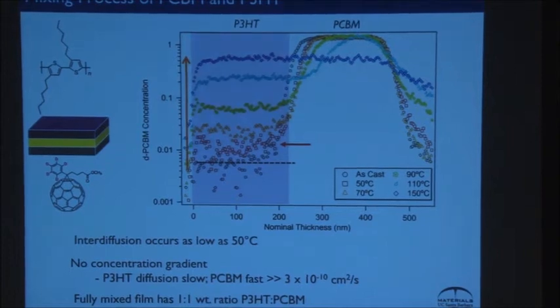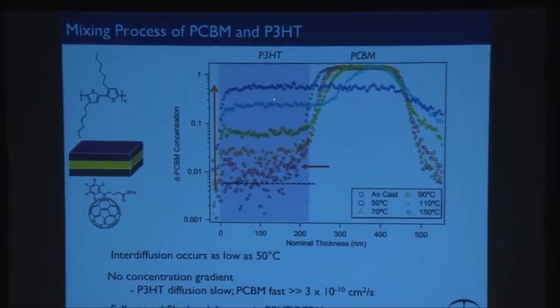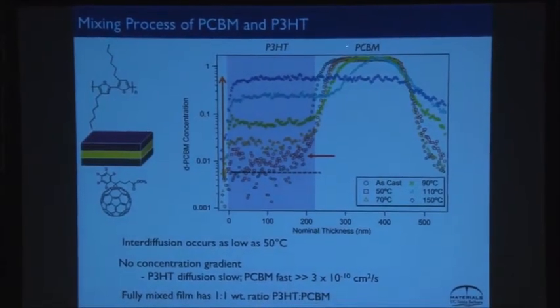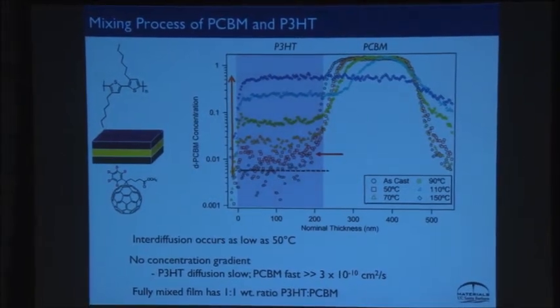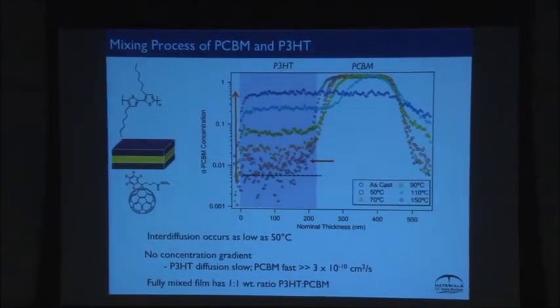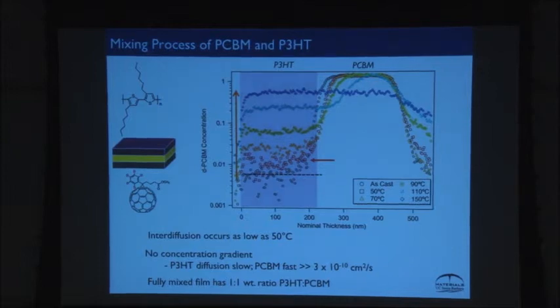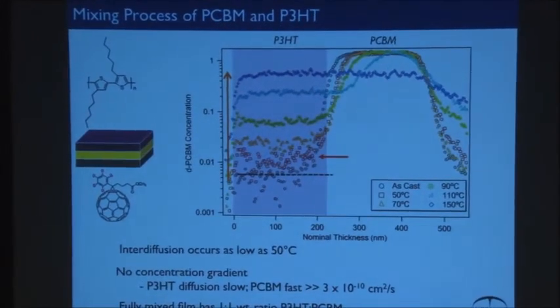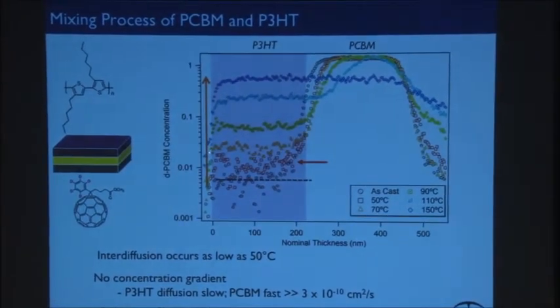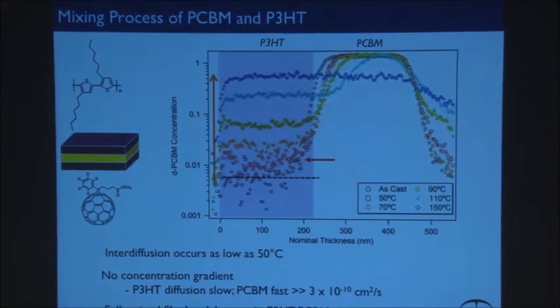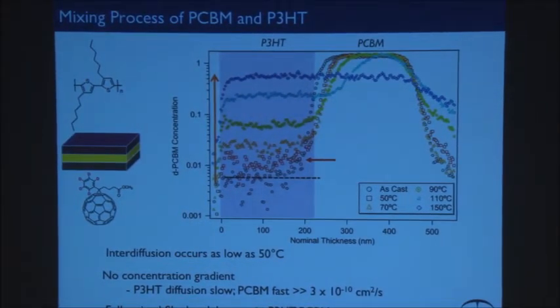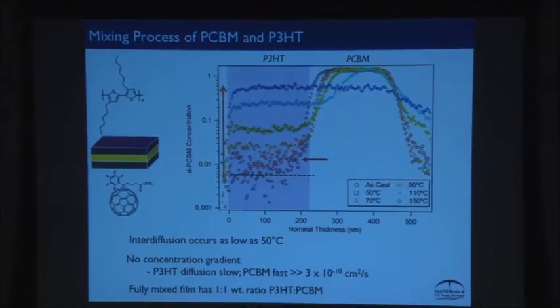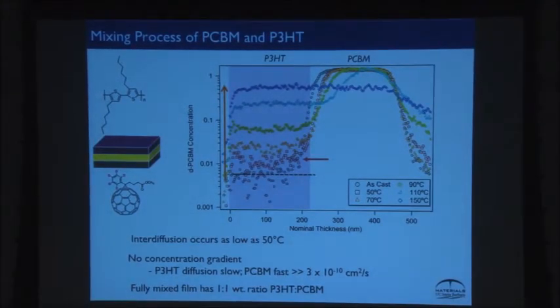We tried to sort this out. No matter how fast you quench the sample, you could never get a diffusion profile that looked kind of Fickian. We could actually do this now with laser spike annealing, but the time scale to do that is sub-millisecond. Okay? What that tells you is the fullerene diffuses extremely quickly. And I'll show you some more quantitative numbers later. And you get kind of this mixture that you actually see in the blends that work well. So it was quite interesting to us.